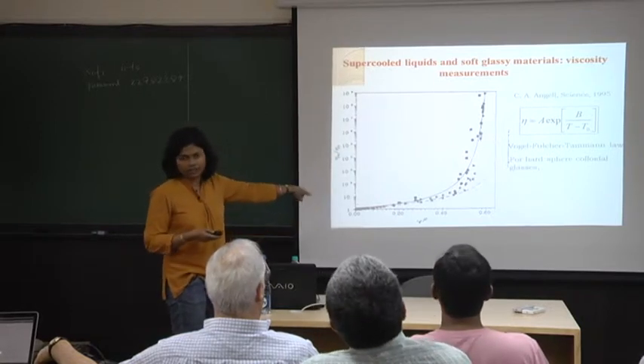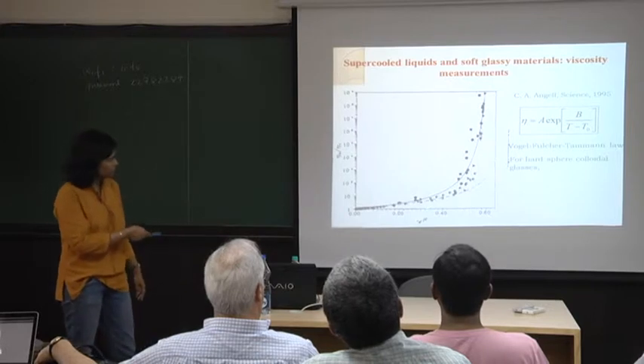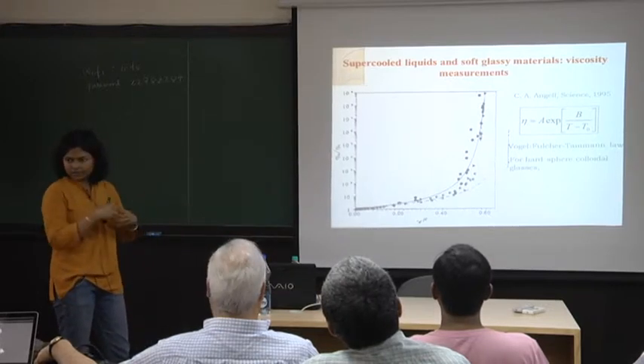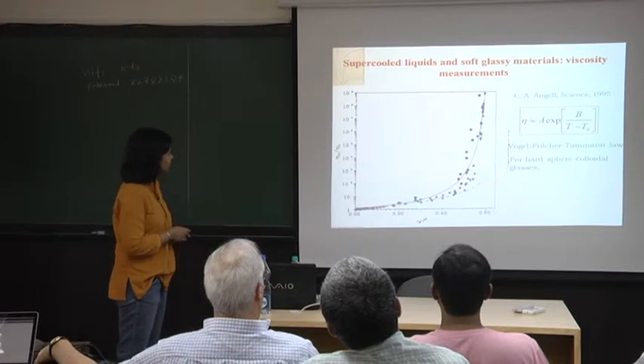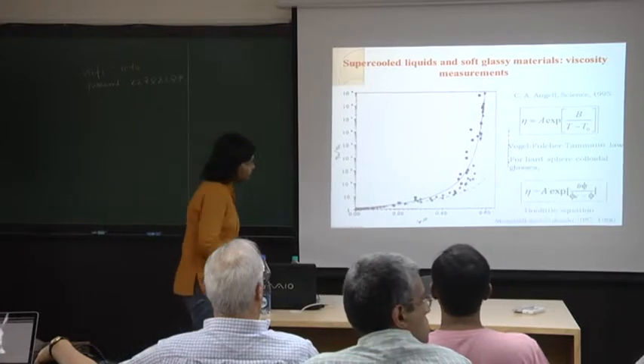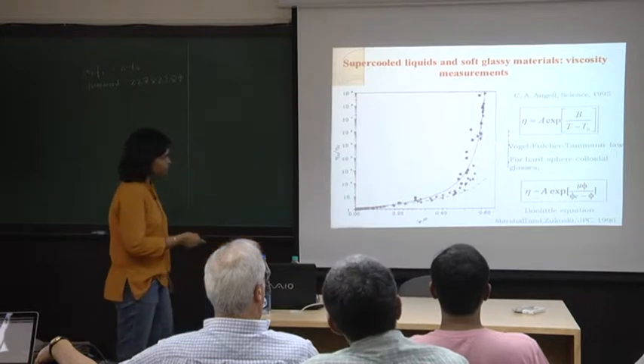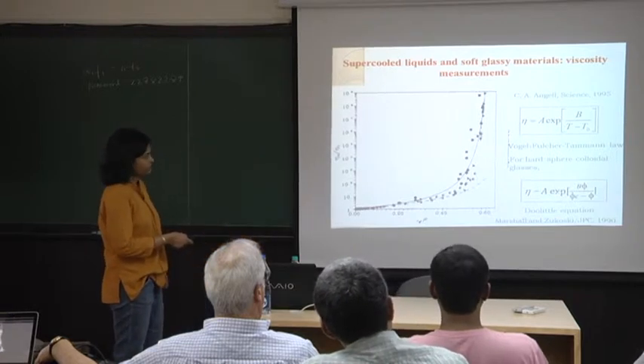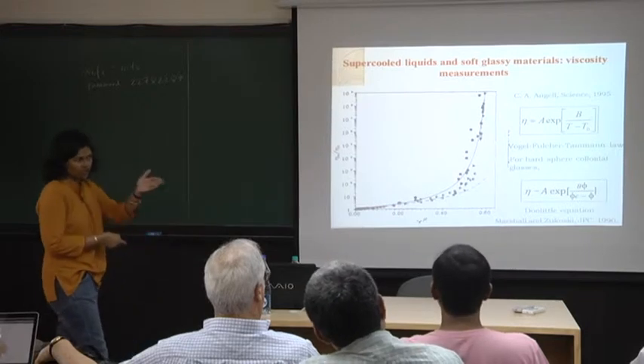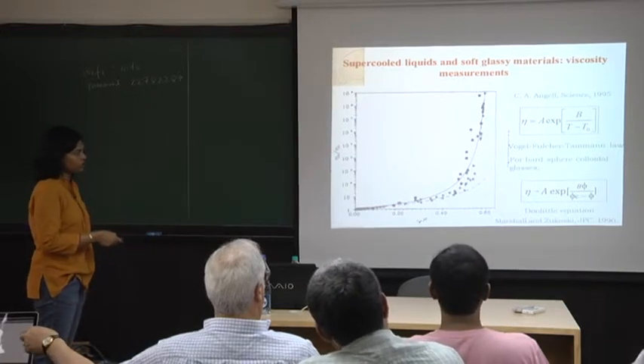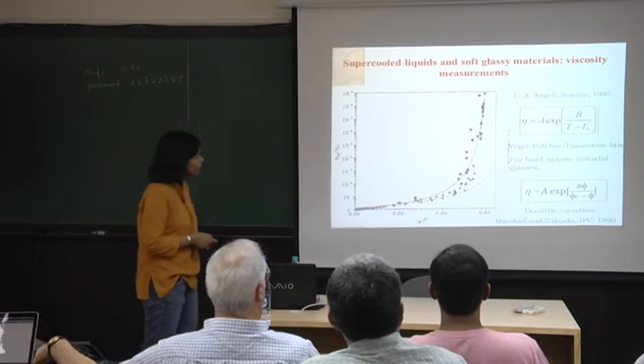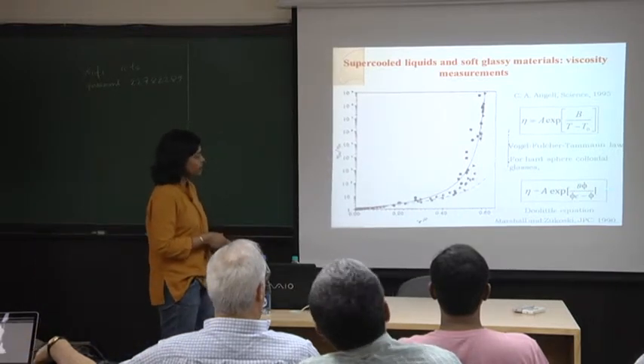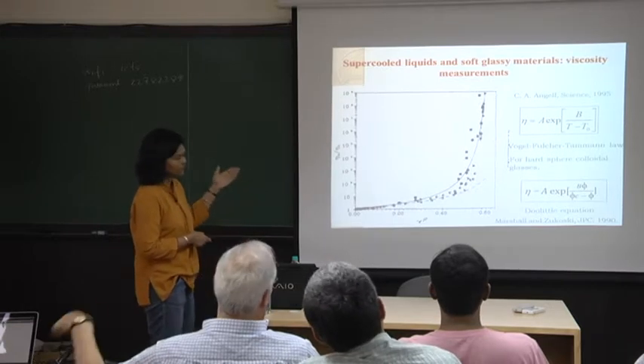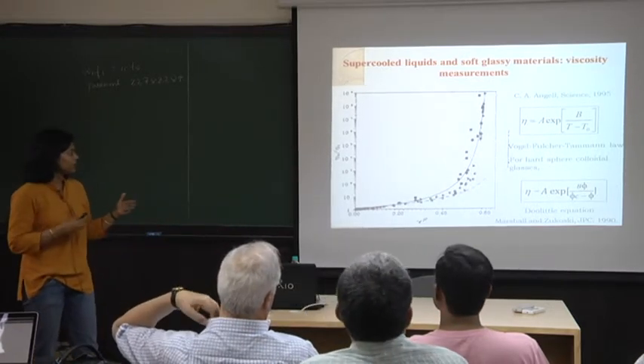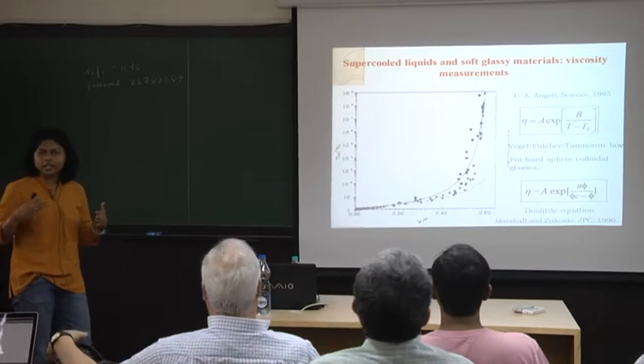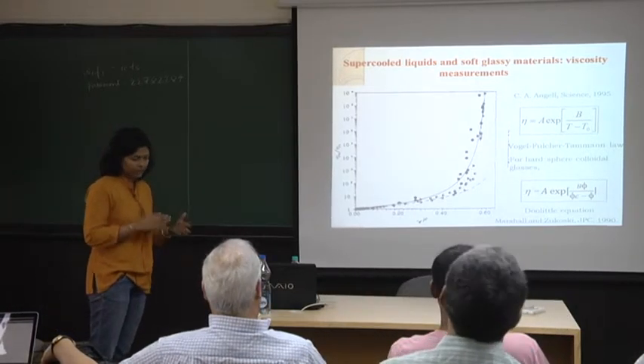This is for colloidal, again, different kinds of colloids. But what you've done is you're packing them more and more. So these are all colloidal spheres, and you measure the viscosity, and you can plot it, you can fit it to something called a Doolittle equation. And you can see here, phi c is the random close packing fraction that Shrikant told you about. Experimentally, this number is something like 0.635. So this is basically a blind fit to the data. Phi again is the volume fraction, and you can see that in the case of colloidal particles, increasing the volume fraction is really analogous to decreasing the temperature in a supercooled liquid.